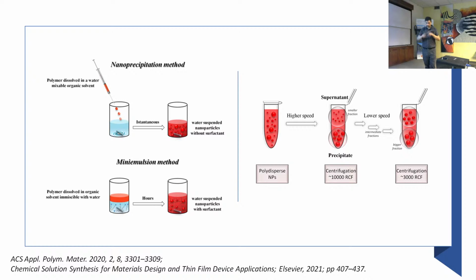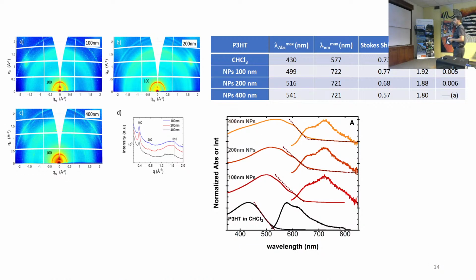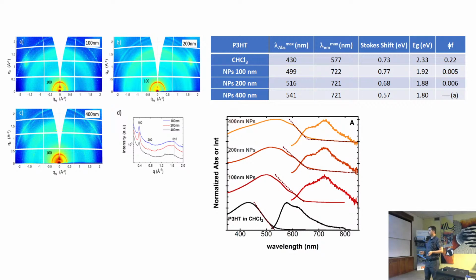And depending on the rotation of the centrifugation, you can get in the supernatants different types of nanoparticles, different sizes. And so we can create nanoparticles with sizes like, for instance, 100 nanometers, 200 nanometers, and 400 nanometers that we measure by dynamic light scattering and by SEM. These particles were studied by synchrotron as well, and they displayed some crystallinity features. So actually they are polymorphic, they have amorphous and crystalline features in the nanoparticles. We believe that most crystalline part is located in the core of the nanoparticle.